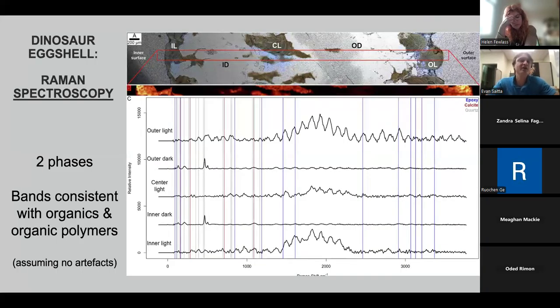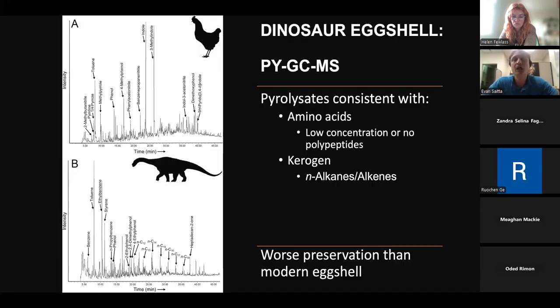Now, we examined these under Raman spectroscopy. The Raman spectroscopy definitely shows two phases, the recrystallized and not recrystallized portion of the eggshells. There's various bands that are consistent with organics or organic polymers. However, there's currently a lot of debate about this method on some of these fossil samples and whether or not there are spectral artifacts as a result of background fluorescence in some of these samples. And so that's something to keep in mind. But we can use further methods to look into this.